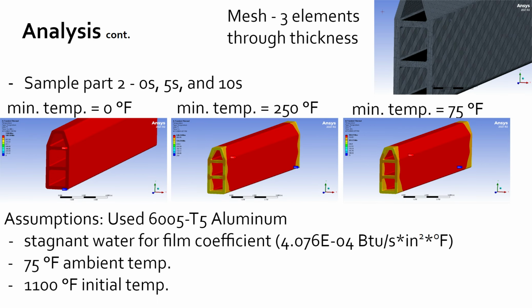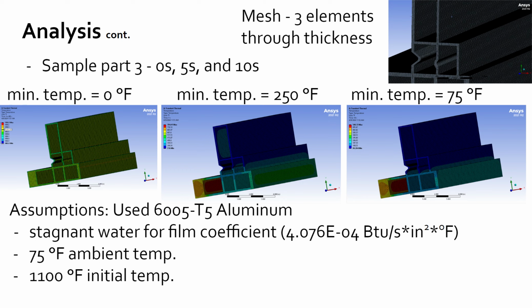This one depicts the second sample that Shape gave us, showing another analysis, which was also done in ANSYS, a thermal transient heat transfer analysis of that second part. And then this is the third and final sample part that Shape gave us, which also shows how it cools from 1100 degrees Fahrenheit to the ambient temperature shown in the assumptions.